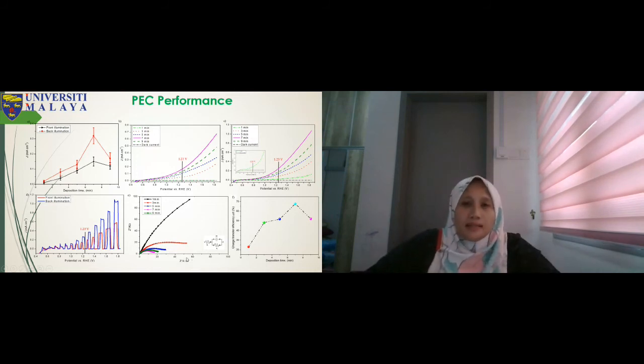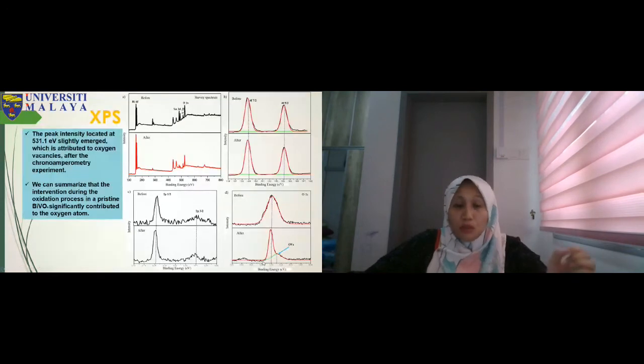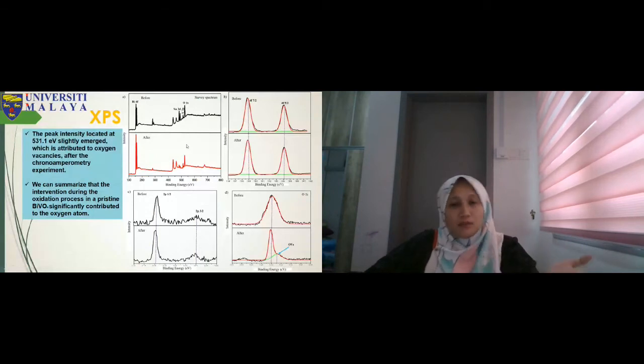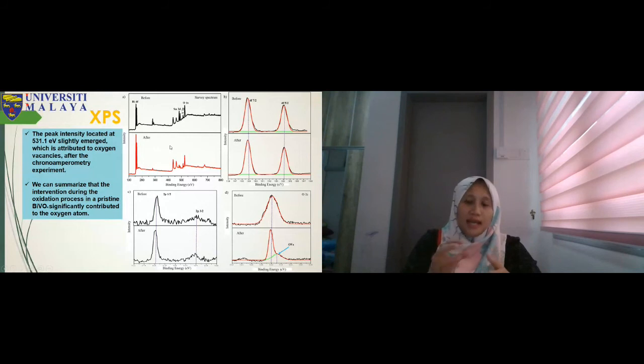Next, the XPS. The XPS analysis is important because we want to check the elemental analysis. For the XPS, the sample was tested before and after we ran the chrono analysis, the stability test, for 30 minutes. The sample was tested by XPS because we want to show the oxidation in our sample during the stability test.